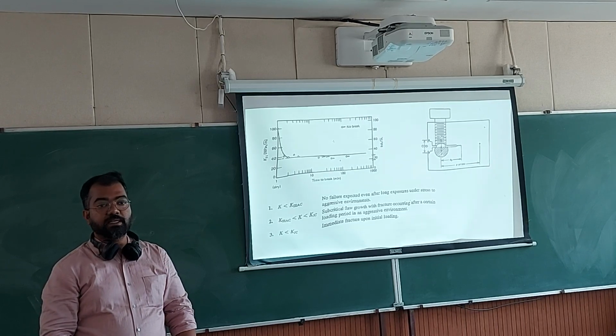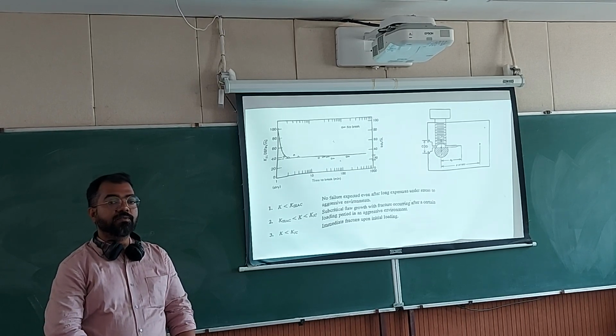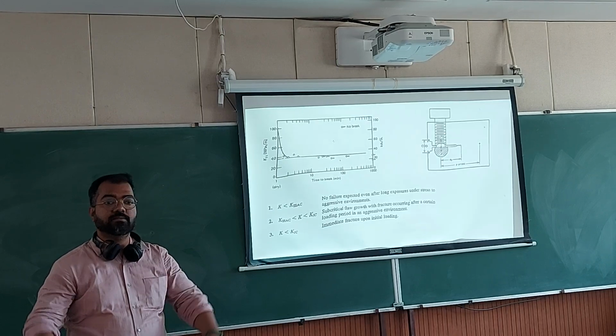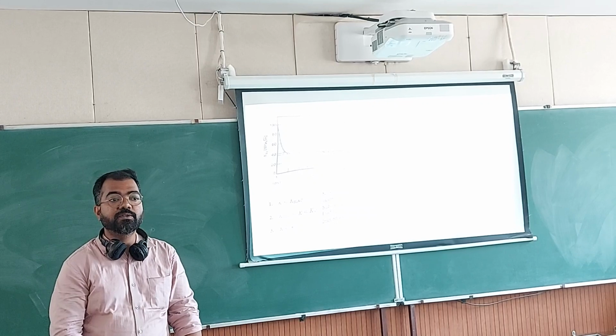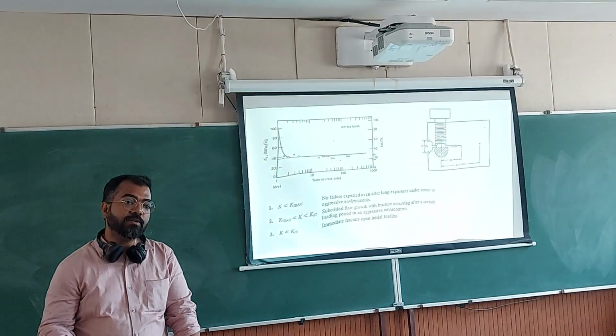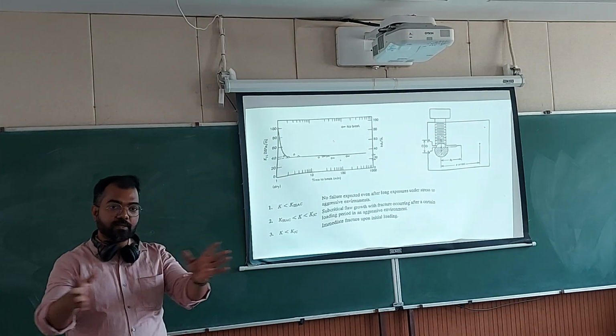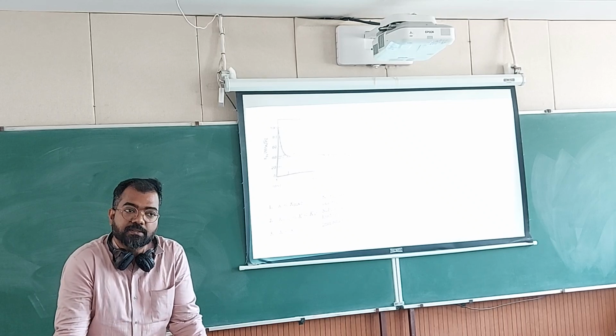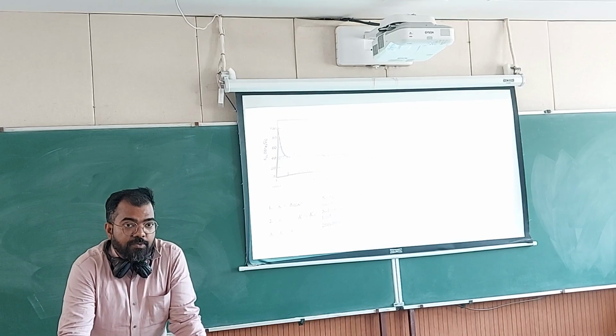If I put my steel in chloride and if I put my steel in ambient environment, in both cases I am getting two different K1Cs. One K1C is telling me that if you go beyond this value in ambient environment, then the material will have a catastrophic failure, right? This value is 180 MPa root meter, let us say. Then you put the same material in chloride environment and this value drops to 80 MPa root meter.